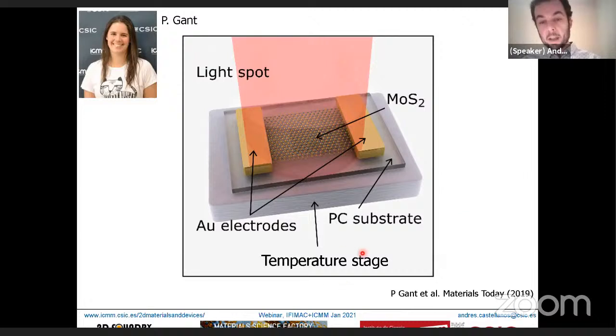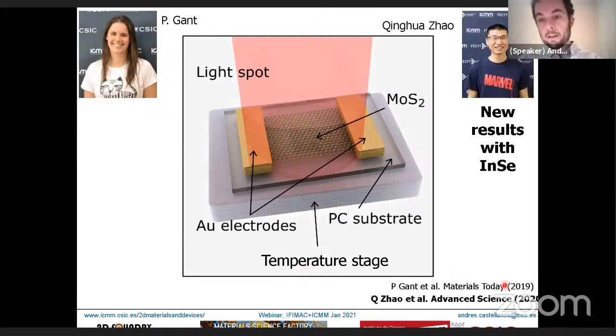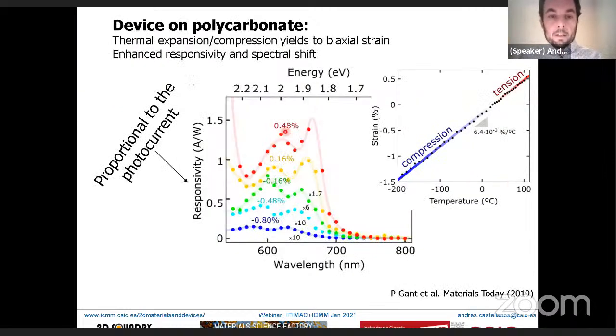By changing the temperature of the substrate with the temperature stage, we can change the amount of strain we apply to our material. Now we also have new results from Tsinghua on indium selenide, which has even larger strain tunability.